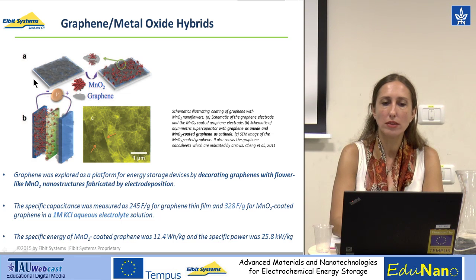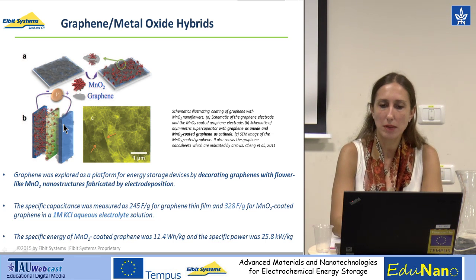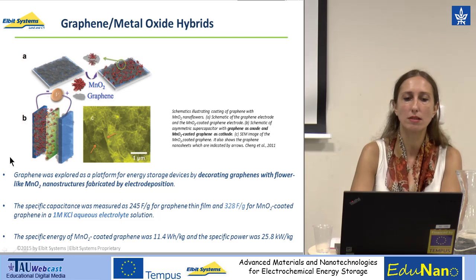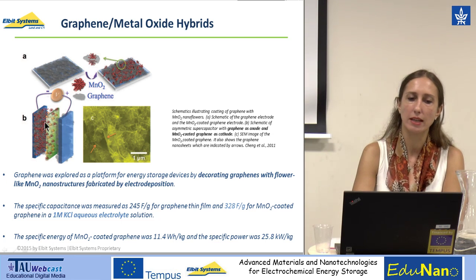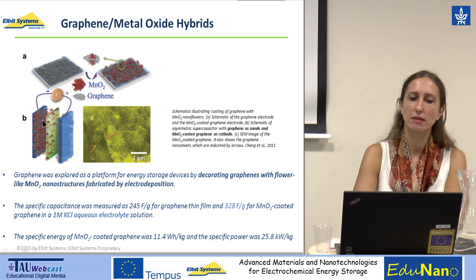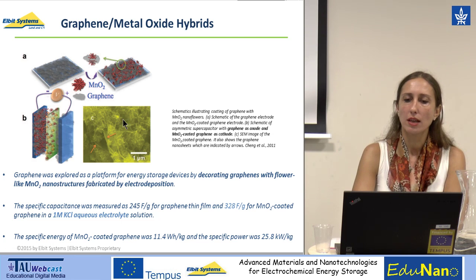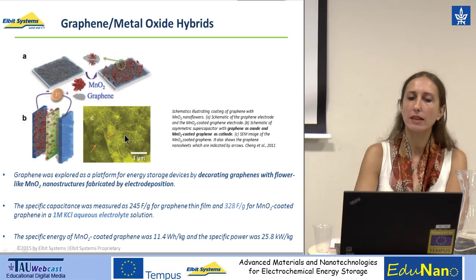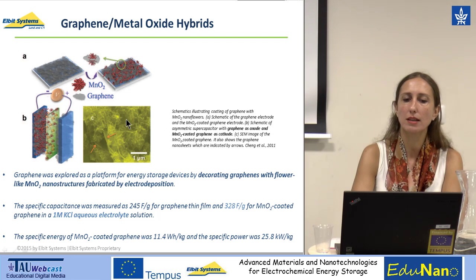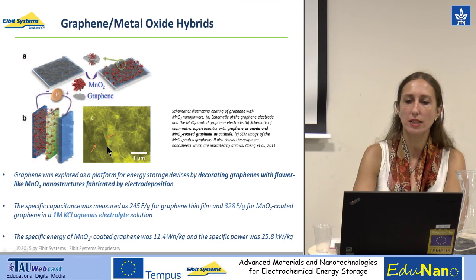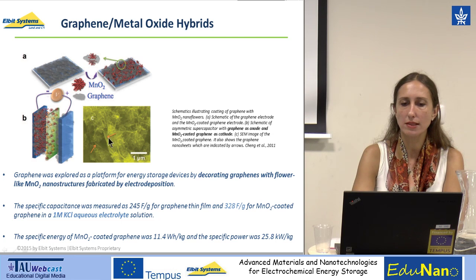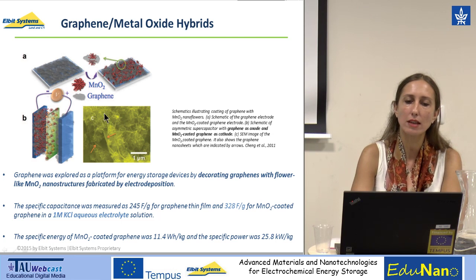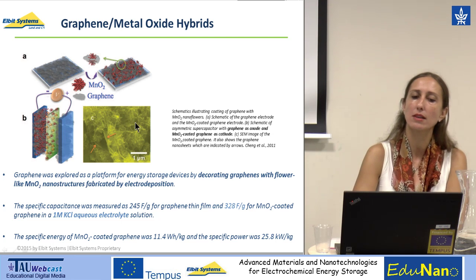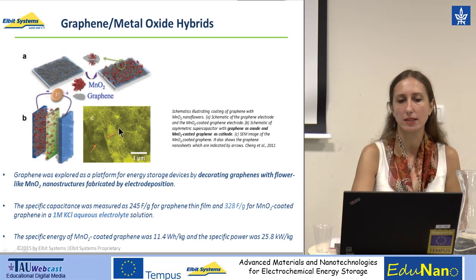You can see the coating on top of the graphene electrode, and the schematic asymmetric supercapacitor with the graphene as anode and manganese dioxide coated graphene as cathode. This is the scanning electron microscopy image of the manganese dioxide coated graphene. It shows the graphene nanosheets indicated by these arrows here, and what you see are these kind of nanoflowers, which are the manganese dioxide particles on top of the graphene sheets.